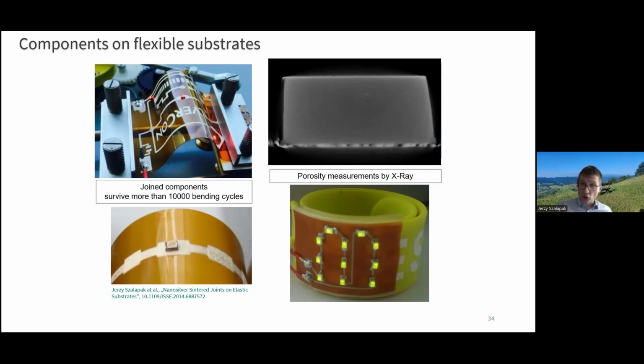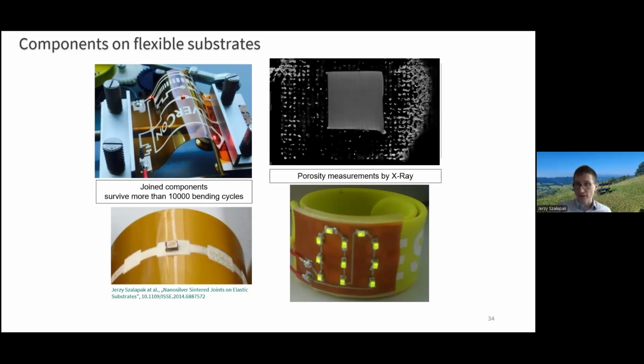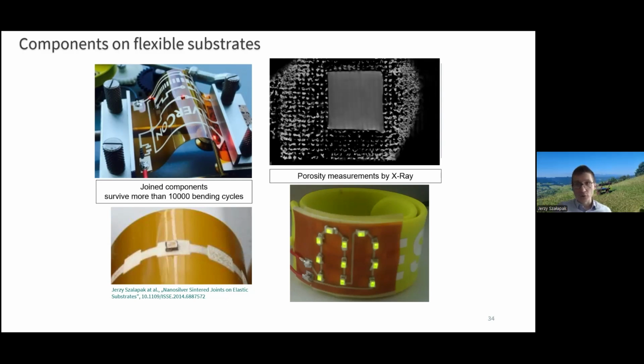So the silver sintering method would allow us for making flexible joints that would easily survive 10,000 bending cycles. We had some samples, but not in such amount that it's statistically important, that would survive 20 or even 30,000 cycles. We were just curious. And the resistance change was within 10% of the initial resistance in our best composition.